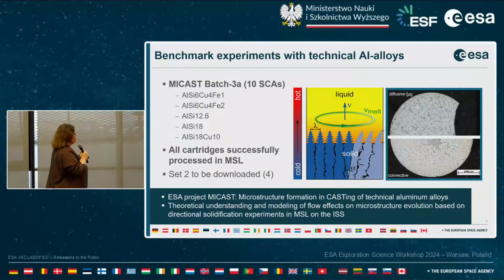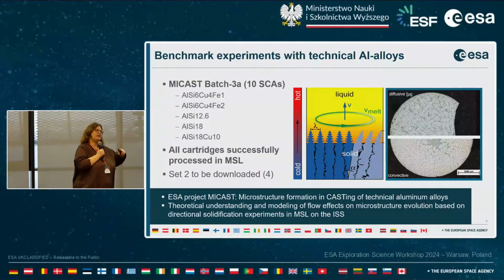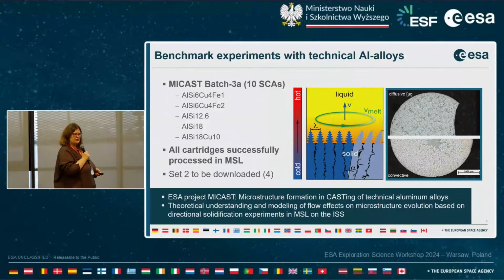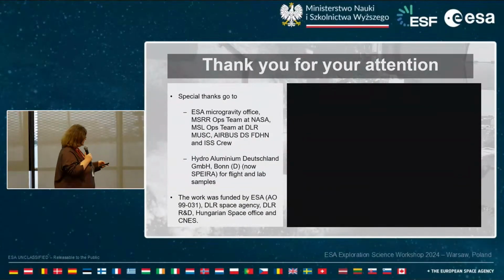When you look at the microstructure solidified with a rotating magnetic field, you see a change in the dendritic network, but in the sample center you see the strong macrosegregation. And this is an effect of the induced fluid flow structure. Because your sample is not endless, you stir it, you have a fluid flow parallel to the growing interface, but you will create convection rolls in axial and radial directions, transporting solute-enriched liquid towards the sample center, and you will finally